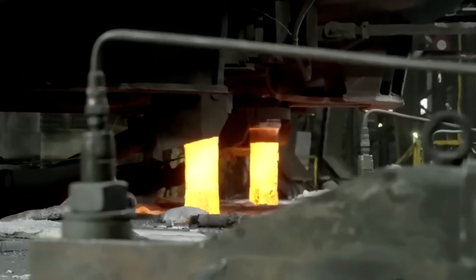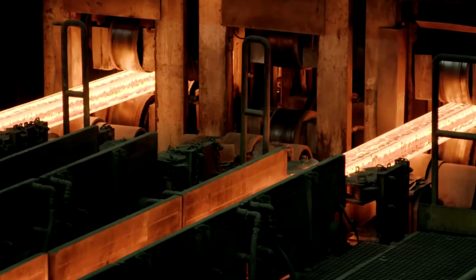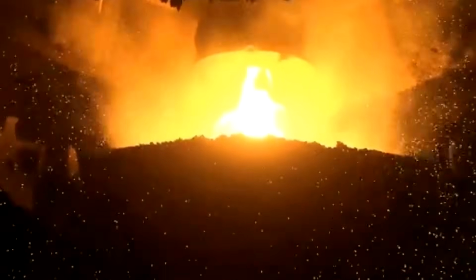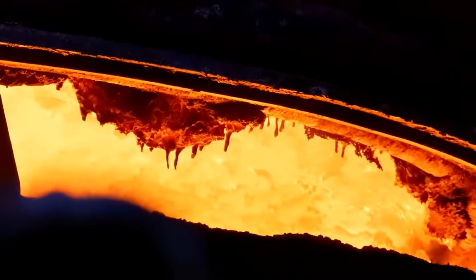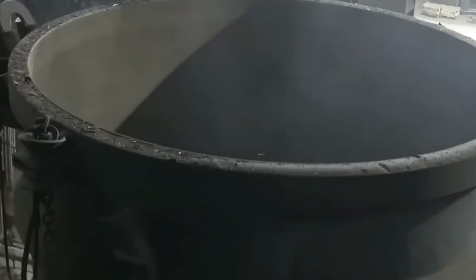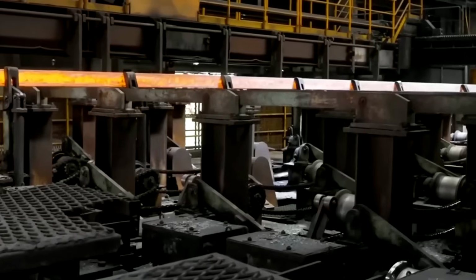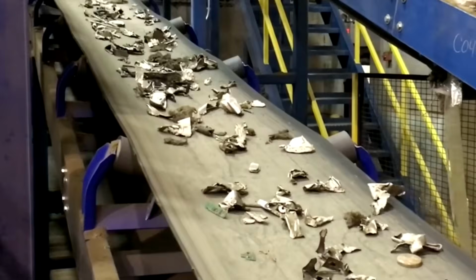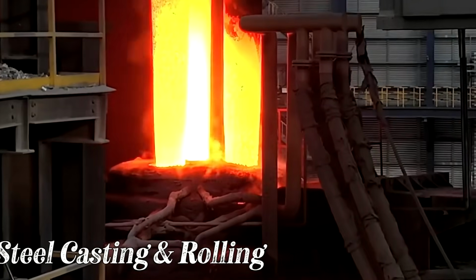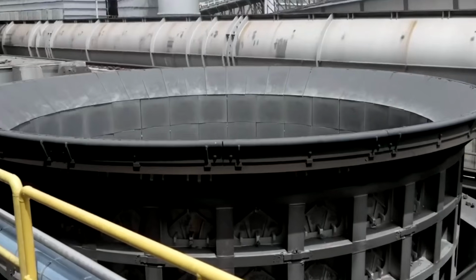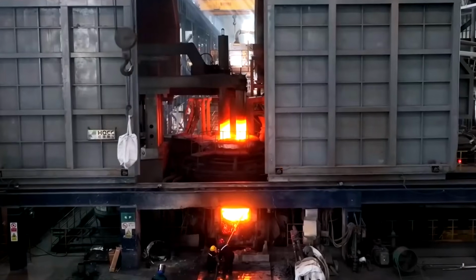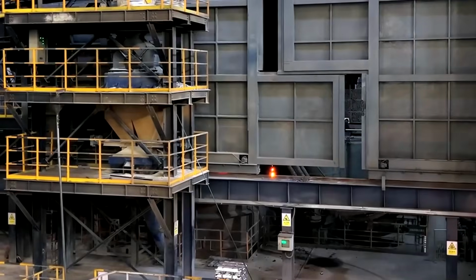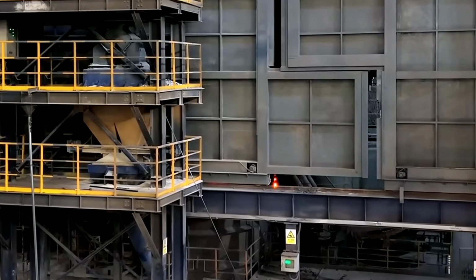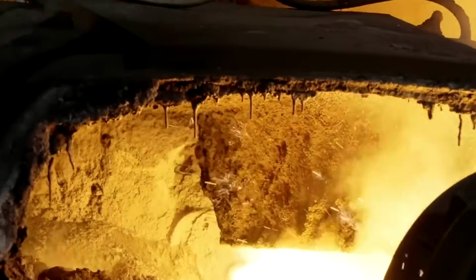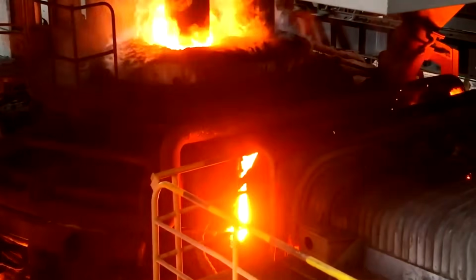150 tons of bundled scrap steel are charged into the deep chamber of an electric arc furnace to begin the process of physical rebirth. Why is such intense electrical power required for this transformation? The metallic mass appears solid and impenetrable at first glance, but the energy of the arcs soon changes its state. Extremely powerful electric currents strike down into the steel mass with a deafening hum, driving internal temperatures beyond 2,700 degrees Fahrenheit. Within just 40 or 50 minutes, the entire load of solid scrap melts down completely.